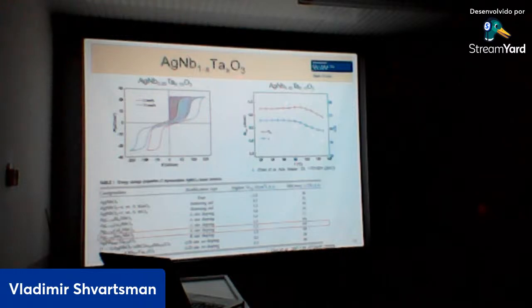So in this material, when we replace niobium not with manganese but with tantalum, people show that again the temperature stability of energy storage parameters will be good. So we have recoverable energy about 4.4 joule per centimeter cube in a pretty broad temperature range, and also our efficiency is more than 60%.